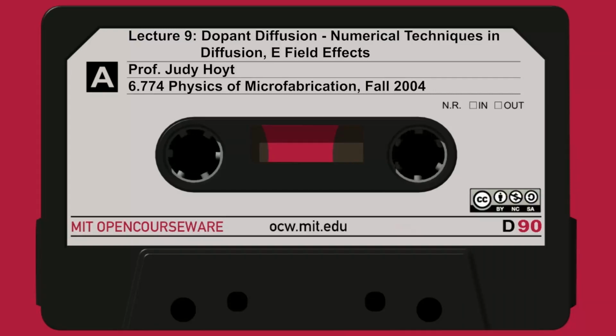But you may have 2 different species diffusing. And in the case where the species are at different concentrations, the electric field term can actually cause an even larger change in the diffusivity of the low concentration dopant. So let's look at a particular example shown on slide 23. What we're showing here is concentration as a function of depth. The red curve is the high concentration, let's say the high concentration arsenic profile. The initial arsenic profile was ion implanted or something, it looks like this, as shown in the solid red curve. The background doping is initially all constant. It's p-type, so just boron, shown by the solid blue line.